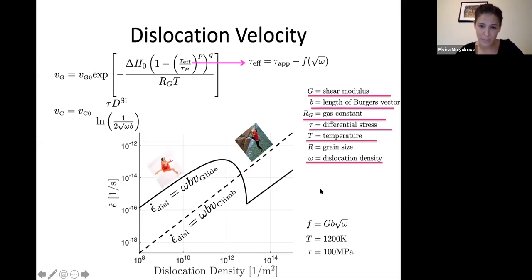The main takeaway from this is that because the rate at which the rock is deforming when in dislocation creep is dictated by the velocity of the dislocations, the rate at which the dislocation moves, and what that rate depends on, whether it's stress, how it depends on temperature, how it depends on the presence of other defects or vacancies, will be determined based on the mechanism by which the dislocation moves.